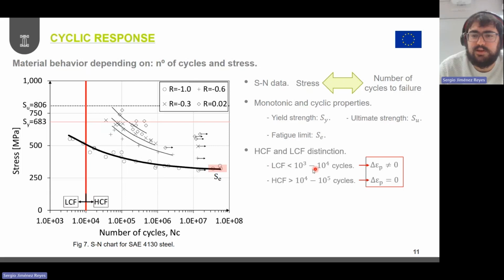And usually this is related with the number of cycles necessary to fail that particular sample or that particular material. Meaning that if fewer cycles are required, then these failures are related with what is called low cycle fatigue. And when more cycles are required, high cycle fatigue is then the phenomenon controlling the degradation process. But indeed, this is just the result, so this is when the failure takes place. But this is not really describing the phenomena controlling the degradation process along the fatigue phenomena.